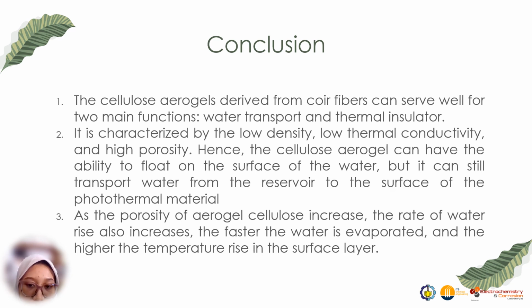Hence, the cellulose aerogel has the ability to float on the surface of the water, where it can still transport water from the reservoir to the surface of the photothermal material. As the porosity of cellulose aerogel increases, the rate of water rise also increases. The faster the water is evaporated, the higher the temperature rise in the surface layer.